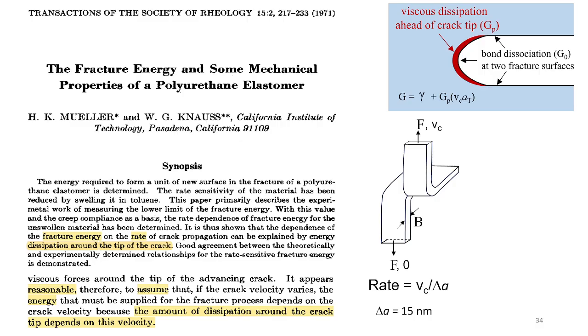So, in fact, there are theoretical attempts trying to compute what this term is by relating it to the rate of crack propagation. Since you have to think about dissipation, there you need to convert this velocity into rate. In converting that, you must introduce a length scale. The only length scale they can introduce is an unphysically small length scale. But people are happy you can fit the data. So they imagine that this crack propagation involves a length scale of 15 nanometers.